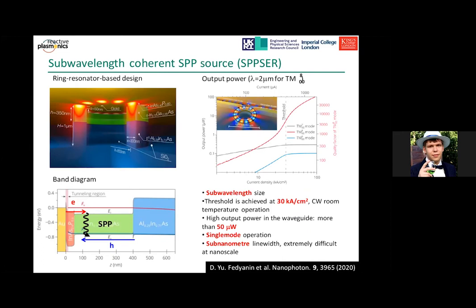Another optoelectronic part, which I'm going to show, is the opposite, focused on converting electrical signals into light. That's our contribution to the design of a sub-wavelength coherent surface plasmon laser. For this, we chose the ring geometry, a ring cavity based on standard III-V semiconductor technology, coupled with a gold film on top. This structure utilizes very efficient electron injection through the shallow Schottky barrier at the interface, and is expected to show a threshold at about 30 kiloamps per square centimeter at room temperature with single mode operation, and we expect it to have at least 2 orders of magnitude higher efficiency than conventional electrically pumped plasmon lasers.